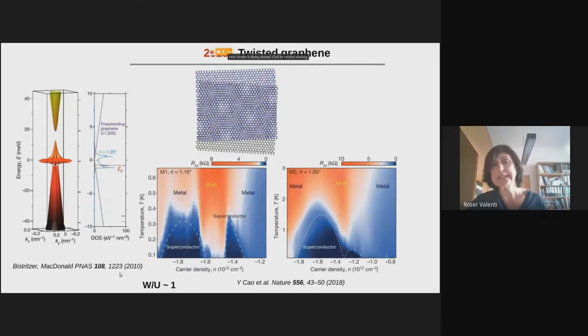So in fact, in 2010, Bistritzer and Allan MacDonald predicted that if you take two layers of graphene and basically you rotate one with respect to the other, then the electronic properties of this twisted set of two layers of graphene are going to be very special. So it's going to have, at the Fermi level, as you know, whatever happens near the Fermi level is what is important for the transport properties of our system and what is important for such properties that I was showing to you, like superconductivity and magnetism.